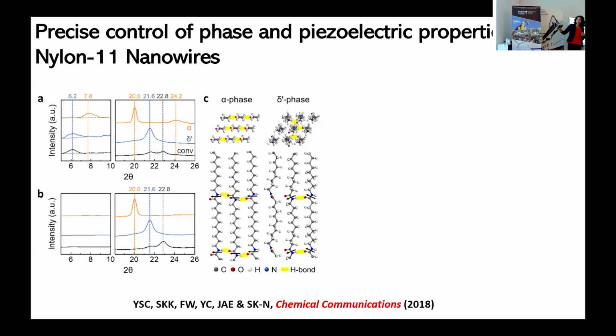Normally you have the thermodynamically stable alpha phase, where you have these chains that are very strongly hydrogen bonded. There is a dipole present, but there's not much you can do with it. They're actually very strongly held in place. You cannot change the polarization quite easily. So this doesn't really give you a very strong piezoelectric response. Whereas this delta prime phase, which we don't normally see, is a metastable phase with a rotatable dipole moment. We did some molecular simulations to work out what phases would likely give us the largest polarization in the chain, and this is the one that we were after.